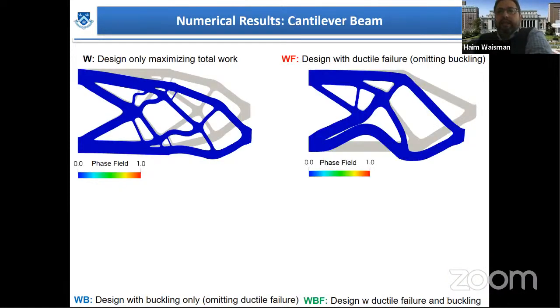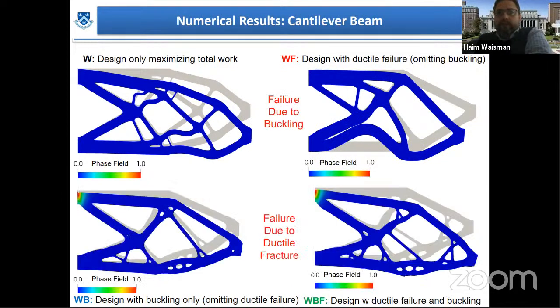So we see that these are the structures that are obtained using this optimization. What we observe is that the first row is essentially failure due to buckling. You see that there are members that buckle because we have not imposed any buckling constraint. On the other hand, if we impose the buckling constraint in the second row, we will see that failure will essentially occur due to fracture. You can see here that we have fracture.